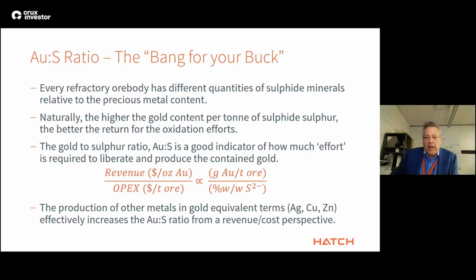Every refractory ore body has unique quantities of sulfide minerals relative to precious metal content. The higher the gold content per unit of sulfide sulfur oxidized, the greater the return for making the effort. Thus, the ratio of gold to sulfide sulfur, expressed as grams of gold per ton of ore to % weight sulfide, is a good indicator of the relative return or revenue per unit of sulfide sulfur oxidized, which is proportional to operating cost.